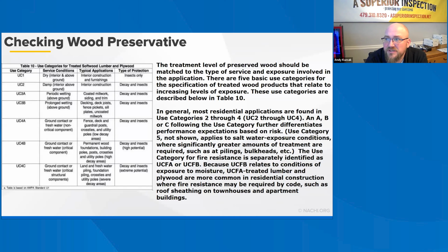Therefore, in cases of exposure to moisture at decks, porches, and balconies, it is recommended that stainless steel fasteners and connector materials be considered. At a minimum, hot dipped galvanization or G120 galvanic coating should be specified for steel fasteners and cold form steel connectors. A G120 coating provides at least twice the galvanic coating commonly used for framing connectors in residential construction. Connectors within the building envelope that are in contact with newer lumber preservative treatments are generally exempted, such as half-inch diameter sill anchor bolts.